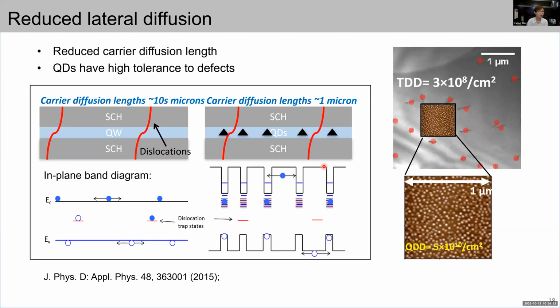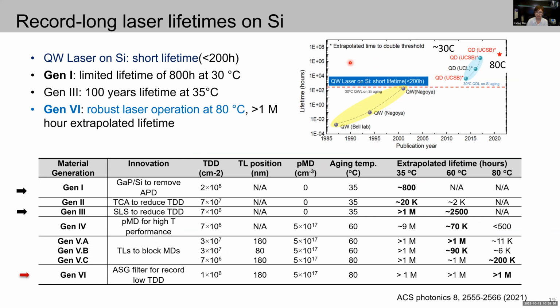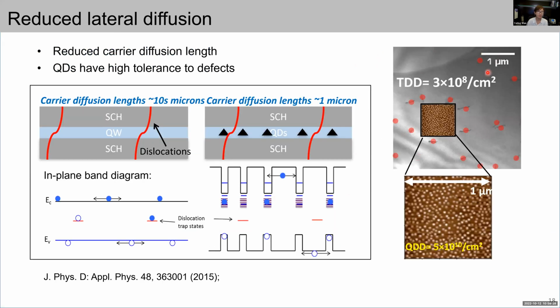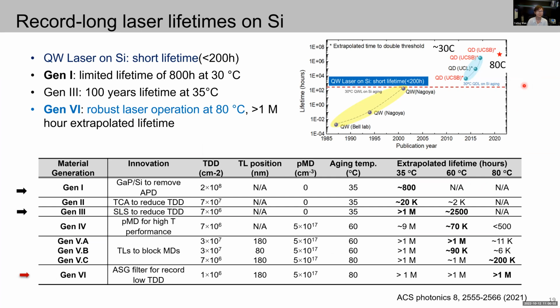And the better lifetime is as I mentioned in this TEM image. Even with a lot of defects in the material, because the quantum dot has very small lateral diffusion and also very high density, these defects can only affect a few dots. Most dots don't diffuse to the defects, so they remain in place and can still work efficiently. So most of the dots can still work, and that's why it has good lifetime. Yeah, thank you.